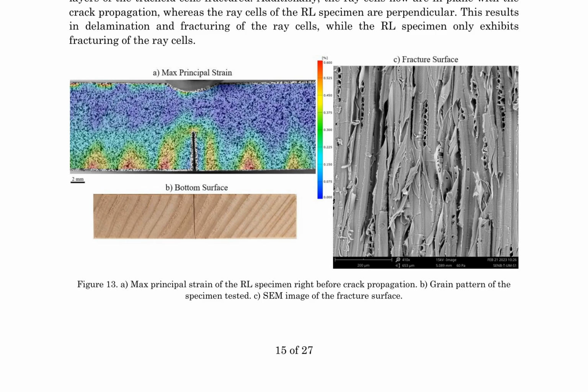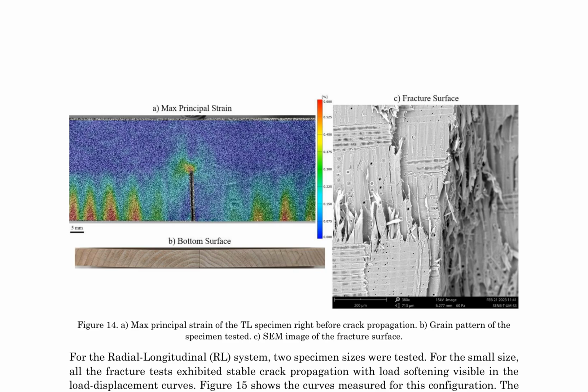Fracture tests on unmodified western hemlock wood exhibit similar crack propagation patterns for both radial-longitudinal (RL) and tangential-longitudinal (TL) systems, with the plane of crack propagation always orthogonal to the neutral axis of the sample. The fracture behavior is relatively brittle, with clean fracture surfaces. However, the fracture surface morphology differs between the two systems, with the RL specimen exhibiting damage in only one layer of vertical tracheid cells, while the TL specimen exhibits damage in multiple layers, resulting in delamination and fracturing of ray cells.